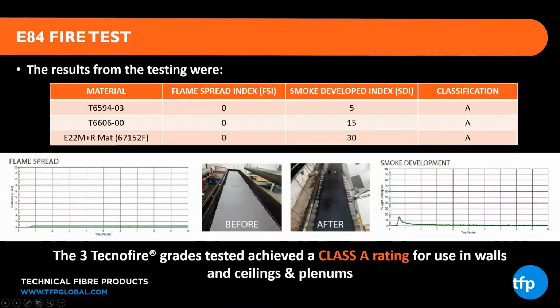We only developed a maximum SDI of 5 for the infusible grade. The next 2 grades were the pre-preg type. The one I mentioned before is a hardened version where we have an epoxy resin system as the matrix. They only added 15 and 30 to the smoke number respectively.